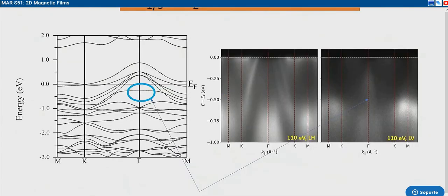Okay, let's look at the band structures that we obtained and try to compare them with our colleagues' ARPES data. So if you again take your band structure out of the calculation and try to compare it with ARPES, nothing matches. You have this flat band here around gamma that is missing in the ARPES data. So again, we said, okay, what happens if we shift down the chemical potential, if we reduce the number of electrons in our system just by a rigid band shift?